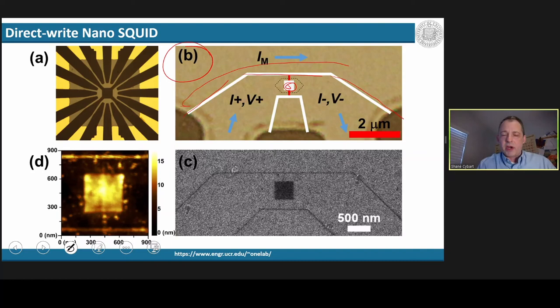And it becomes very strongly coupled because, as you know, the magnetic field falls off is one over R squared. So the closer you can get that current, the better the sensor will be. We also trim down the squid to force these resistances to go up and be much higher. Figure C shows a helium ion micrograph where it's an actual device, and the dark regions represent insulating areas in the squid. So it's very reproducible and very exact to whatever you pattern.